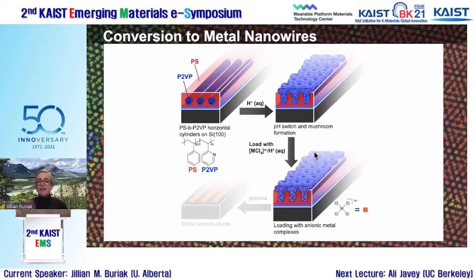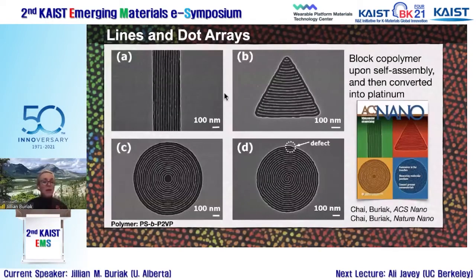And we can then just dip this into a new solution, one which contains an anionic metal salt. So it could be, for instance, PtCl4 2- or AuCl4-, whatever metal you would like, just choose the anionic metal equivalent of that. You load it up, then you do a plasma step, and you end up with a high fidelity nanopattern that has the same center to center spacing and pattern as the parent block copolymer. So you can easily convert this all through wet chemistry, with the exception of just the benchtop plasma unit, into metal nanowires. And so then you can make all sorts of interesting and fun patterns.